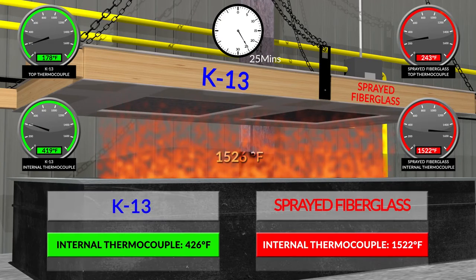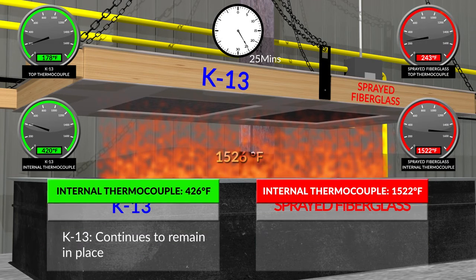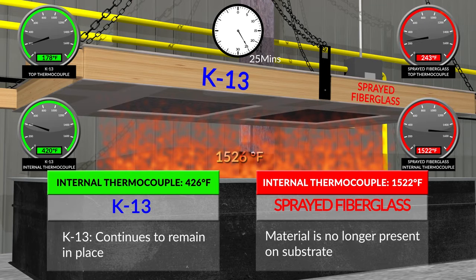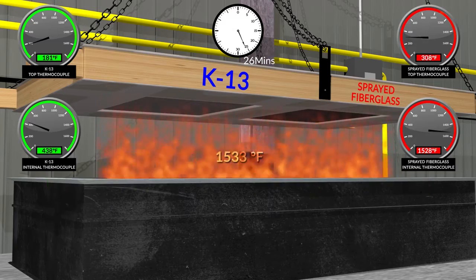At 25 minutes, K-13, internal thermocouple is 426 Fahrenheit. Sprayed fiberglass, internal thermocouple is 1,522 Fahrenheit. K-13 continues to remain in place. Sprayed fiberglass material is no longer present on substrate.